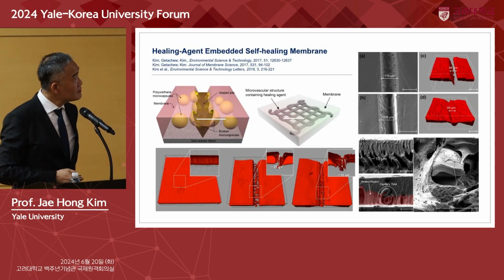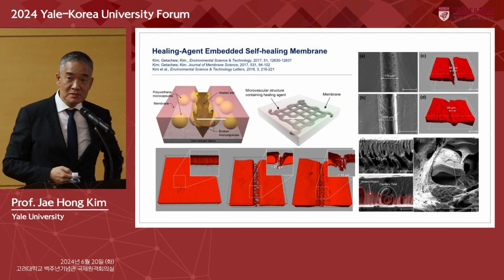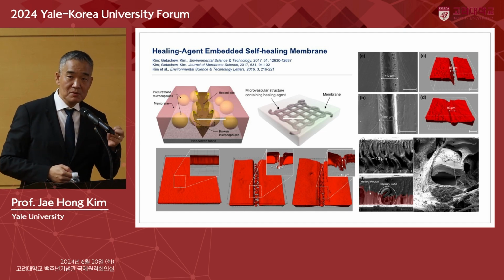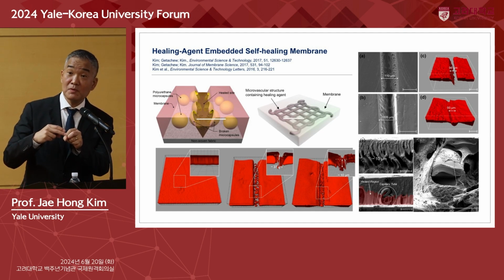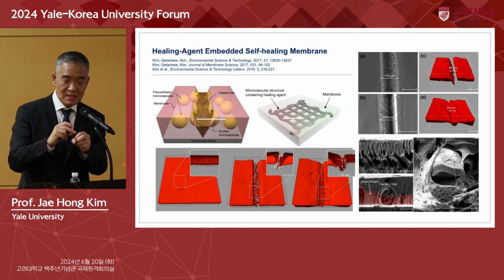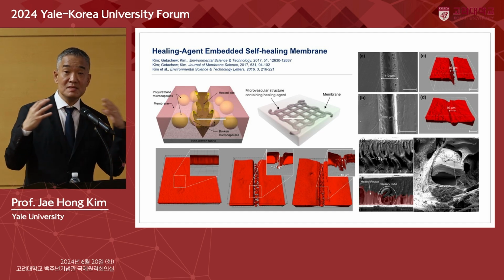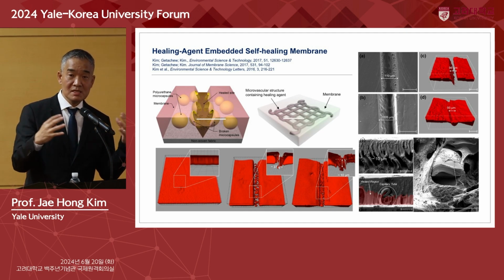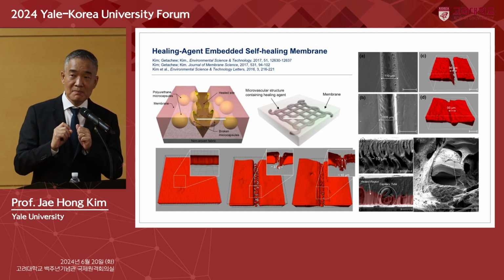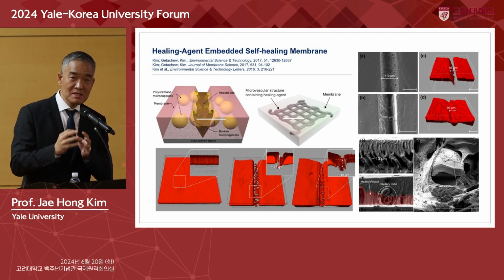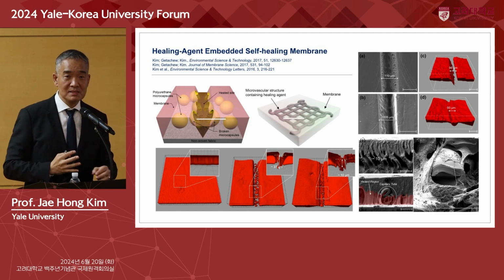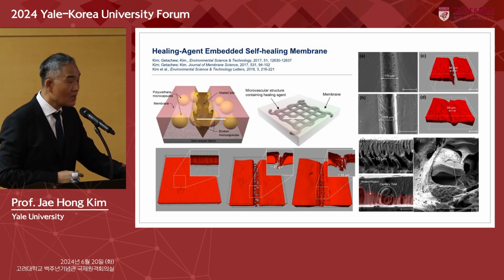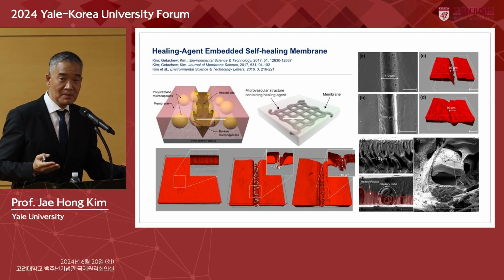The way we did it, this is the first generation. We came up with this microcapsule. We put in super glue, isocyanate, and then we synthesized the membrane containing a lot of microcapsules. When the membrane gets damaged, they release the glue and fix it on the spot. Well, it was at least the first self-healing membrane in the literature.